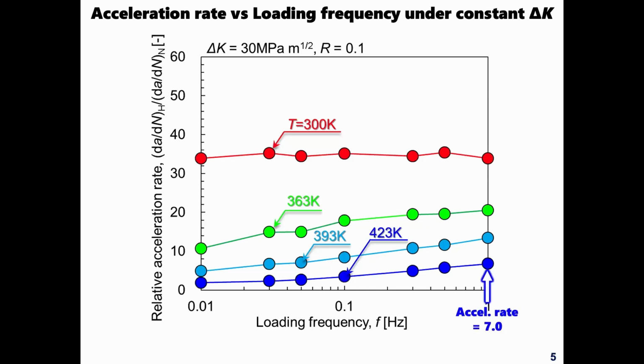At the highest temperature, the acceleration rate of 7 dropped to 1.8 by decreasing the loading frequency from 1 hertz to 0.01 hertz. This value of 1.8 means the fatigue crack growth rate is very close to that in nitrogen gas, so almost no acceleration occurred in this case. These results, including temperature and loading frequency simultaneously, are so important for interpreting the mechanism of hydrogen-assisted fatigue crack growth from the viewpoint of the thermally activated process.